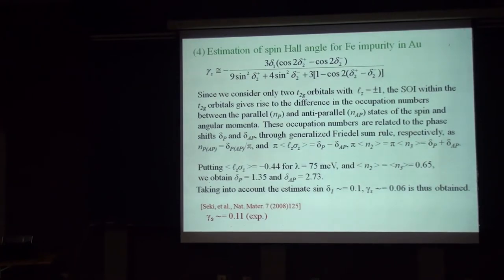Now, the second question of course is very important. From this quantum Monte Carlo calculation, what's the spin Hall angle you get? Using the same formula and we can estimate phase shift and put the phase shift here. And, I would get a spin Hall angle about 0.06. Eventually, that's the same order of magnitude. Although, it's only half our experimental value originally reported.